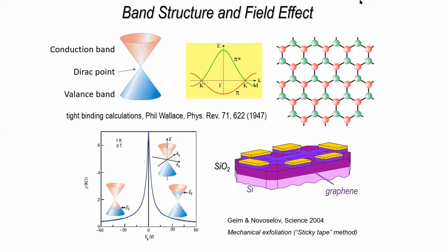I hope he's still listening. Is there any way to use high frequency sound to produce graphene? That seems a bit left field, that question, I have to say, but you may know more about it than I. I'm not aware of such a method. I presume the idea is to break bonds between layers using ultrasound. There are methods which use ultrasound, called liquid phase exfoliation. But it's not just sound, it's also a solvent. You put a crystal of graphite into a solvent, which penetrates or almost penetrates between layers. Then if you sonicate it, it helps the solvent go between layers and separate them apart. So I would say, yes, this is already used, but not just sound alone.